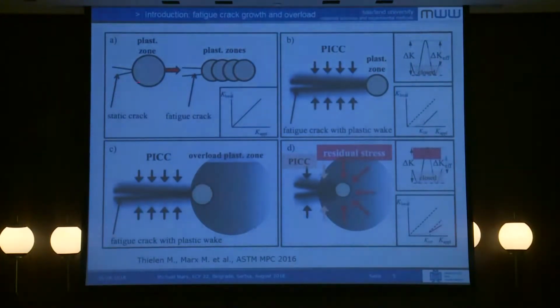First, if you have your static crack, you have the plastic zone, and if you have a cyclic crack, you have your cyclic plastic zone in front of the crack tip, which is a little bit smaller than the static plastic zone. And if you have here your applied stress intensity factor calculated just by the stress and the crack length, and the local acting stress intensity factor, which you can measure, for instance, by the crack tip opening displacement, then you will get here a linear behavior.